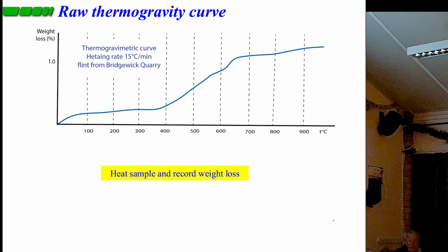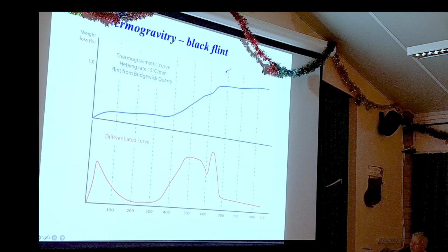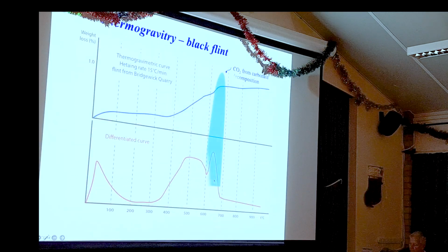So we look at the thermogravimetry curve first. They're not very exciting. This just shows the weight loss and it just gives you a line. But what we can do is differentiate that curve so you can see the loss of individual components. This little jump there coincides with this spike, and is a result of weight loss due to the loss of carbon dioxide as any carbonate in the sample breaks down. There's usually a few carbonate fragments in the flint that will break down at around 600 to 700 degrees, and it gives rise to this spike.